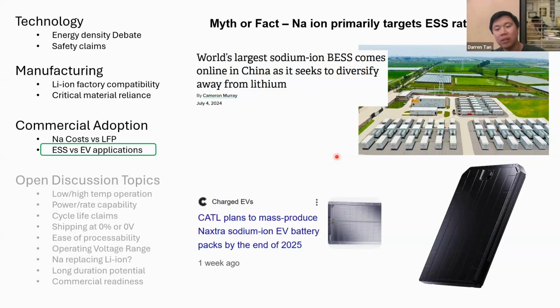To give an example, today, when we install any battery for our homes, for our offices, for our factories, we can only put it outdoors or in a garage, right, behind a fireproof wall. We can't put it in a high-rise building. We can't put it in our bedroom. There are restrictions due to the reality of the safety limits of lithium-ion. But if sodium-ion can overcome these limits, then perhaps safety becomes a more important value proposition than energy density and cost, and will justify it simply because you cannot do it with lithium-ion.